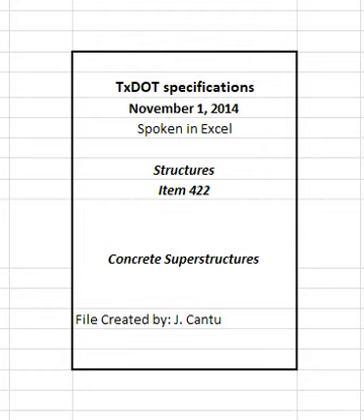4.5.3 Breaking back bridge slabs. Saw the top surface of the slab for bridge slabs and direct traffic slabs of box culverts along the break line to a depth of 1/2 inches before breaking back. Do not cut the reinforcement at the break line. Sever the concrete at the break line. Do not damage the remaining reinforcement within 1 lap length of the break line during removal of the designated portion of the existing structure.